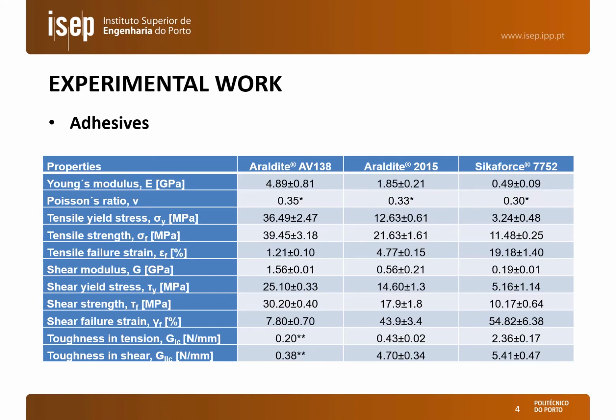The Araldite AV138 is a brittle but strong epoxy adhesive. The Araldite 2015 is an adhesive with intermediate ductility, while the Sikaforce is a highly ductile polyurethane adhesive. We can see the differences between the adhesives, for example, by looking at the last two lines of this table, in which we can see the tensile toughness and the shear toughness with proper values for very brittle adhesives in the AV138 and more ductile behavior in the other two adhesives.